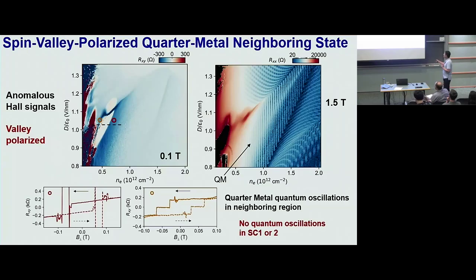At the same time, you can do the quantum oscillation, okay? You apply an out-of-plane magnetic field, and you count the period of this quantum oscillation to tell how many of the isospin pockets are occupied. You find this region here, which is right next to SC1, is a quarter metal. So that tells you this neighboring state is a spin and valley polarized quarter metal. It's not inter-valley coherent because you broke the valley symmetry already. Okay?